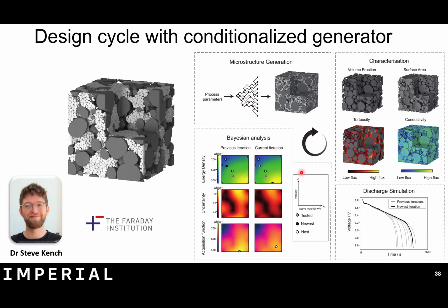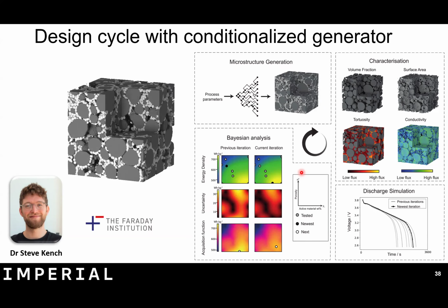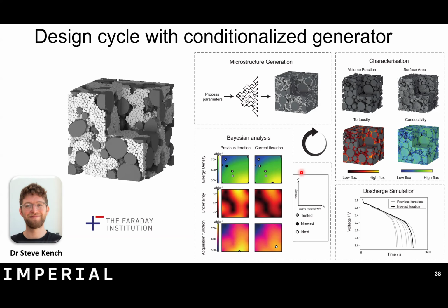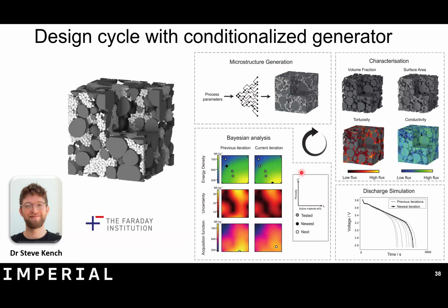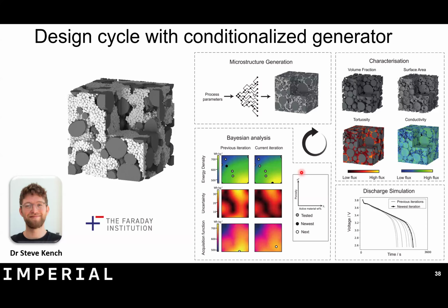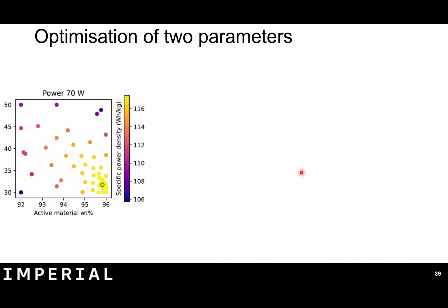So this loop is only closable because the microstructure generator is roughly 1 million times faster than the physics-based equivalent from Sandia only a few years ago. So it's really exciting. And to look at this case study in more detail, if you want to optimize a 4680 cell at low power, which is 70 watts, well, the result says have lots of active material, not much carbon binder. That's the horizontal axis. And the vertical axis is saying don't have very much porosity.